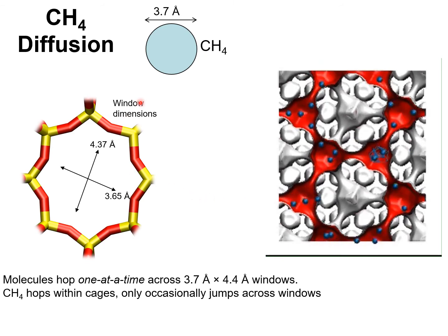Methane is much more strongly constrained at the window. It is able to cross the window because the windows are not completely rigid and have some degree of flexibility. Predominantly, the hopping of methane molecules in DDR is occurring within the cages. As you can see from the trajectory of a single methane molecule, it is located within